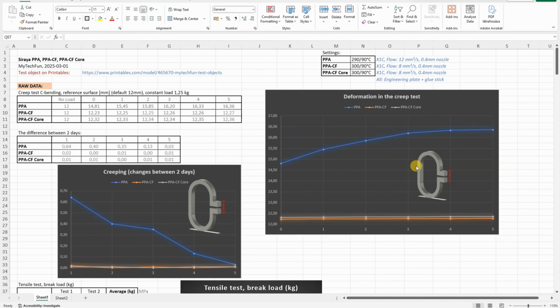On this graph we can see the distance between two reference surfaces, and on the carbon fiber versions almost no deformation. On PPA we can see some initial deformation and some creeping, but the creeping is the difference between 2 days, and that's what we can see on this graph. And the carbon fiber versions basically don't have any additional deformation. On the PPA we can see some creeping even on the 4th day. Compared to these materials it was weaker, but compared to some other average materials this is still very strong.